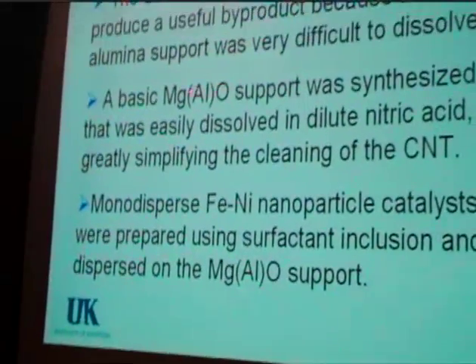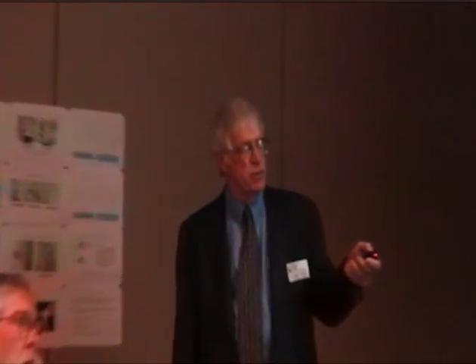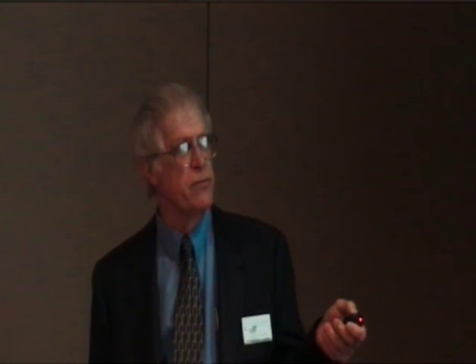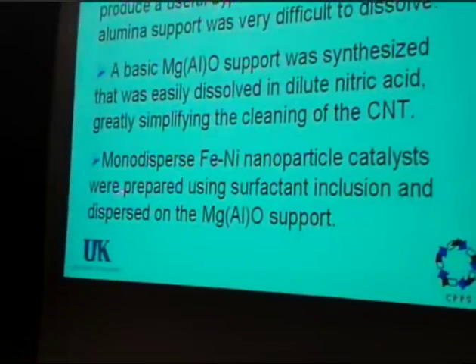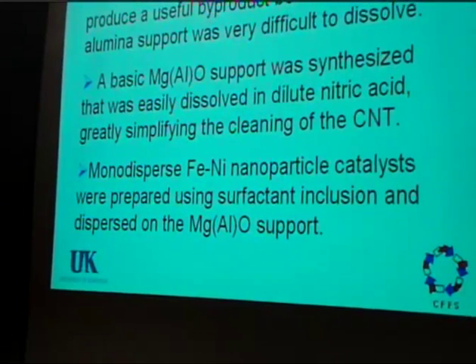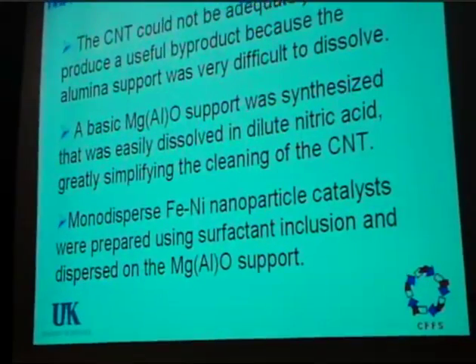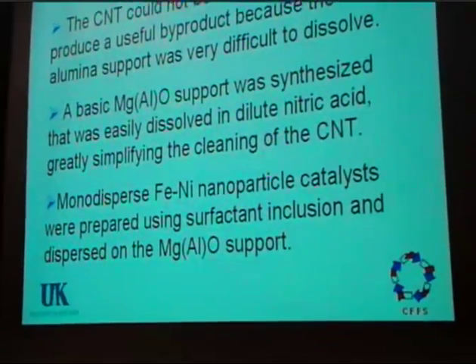This was a magnesia aluminum oxide support, in which the magnesia to aluminum ratio is about 5, and it's formed by calcination of the hydrotalcite compound. This is very easily dissolved in dilute nitric acid, which greatly simplifies the cleaning of the carbon nanotubes. To test this, we focused on our iron-nickel alloy catalyst, since that's the cheapest catalyst that we have. And these were prepared, in this case, we wanted to look at a more uniform nanoparticle size, and so we went to a surfactant inclusion technique.